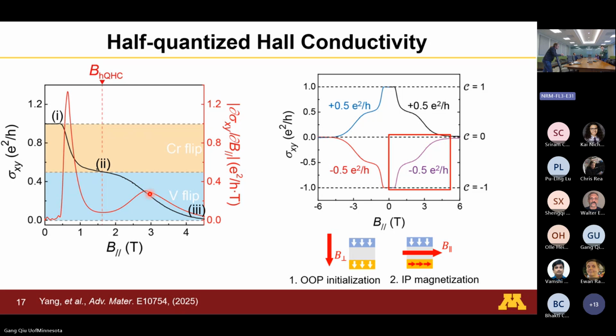So let me answer the magnetic restrictions first. We tried a very simple way. For instance, vanadium-doped samples are easy to magnetize. We basically put a small permanent magnet to our sample. That's enough. A few oersteds is enough to magnetize it, just like a hammer, right? We cool down with the field. In that case, only a few Oe is enough to fully magnetize it. Well, you could call it heat-assisted quantum anomalous states.